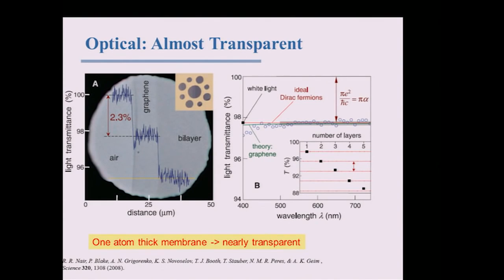Graphene is also optically very interesting. Although this is a single atomic sheet, there are a lot of electrons that can absorb the light, and it is a good conductor, as I mentioned. You expect the light may not go through well. Turns out most of the light goes through, about 98%. Here's the example done by the Manchester group. They actually suspend the graphene over a hole. Here's one monolayer, two layers of graphene. This is just a hole through the air. Then you see that it's slightly darker and more darker here, showing that even if it is a single atomic layer, it absorbs a small amount of the light, about 2%, and most of the light goes through. So it has a kind of interesting optical property.